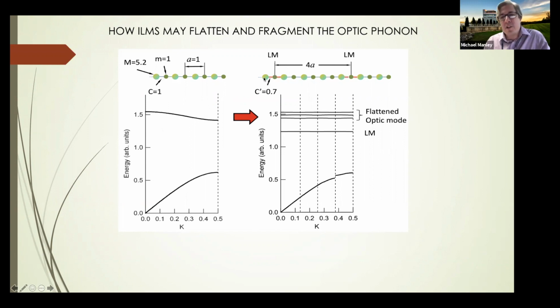But if you want to artificially create a local mode, you can just soften the lattice around it. That's effectively like making the ILM, but kind of cheating, and doing it linearly. When you do that, you basically make a supercell, so you have to unfold it. But what you'll find is that you get a very flat optic band, and you get this local mode breaking off. The reason that happens is that localization begets localization. Once you start putting these soft spots in there, it starts to trap other phonons. At each of these boundaries, phonons that become multiples of this distance become standing waves at that distance. And so this tends to flatten the whole thing. So that's partly why that happens.